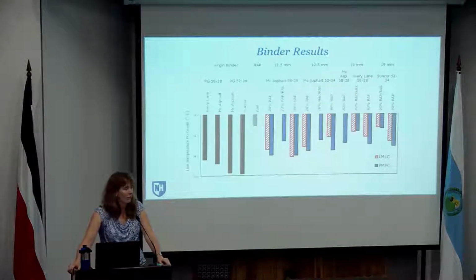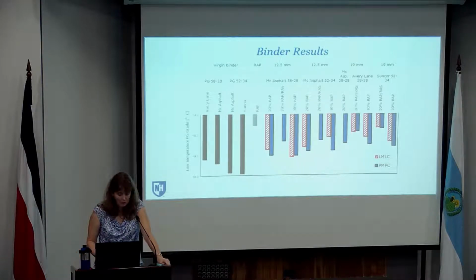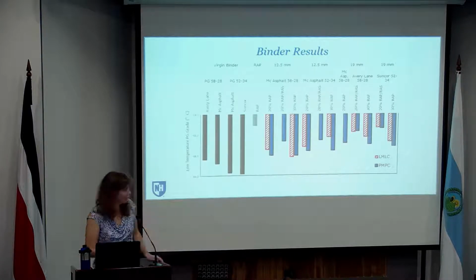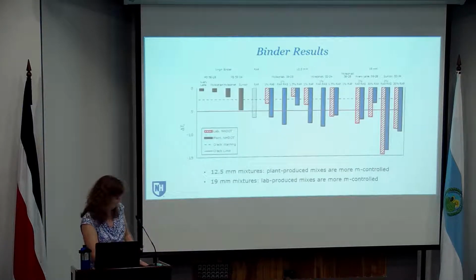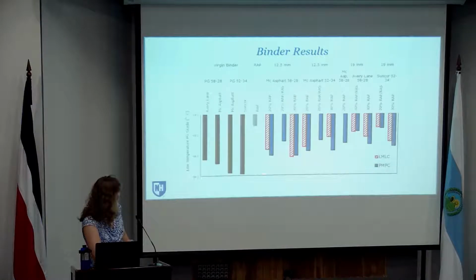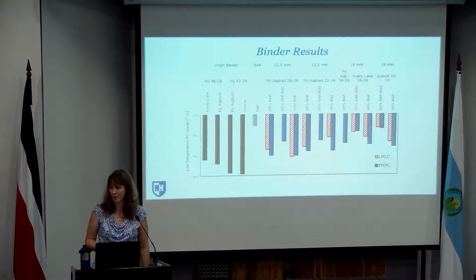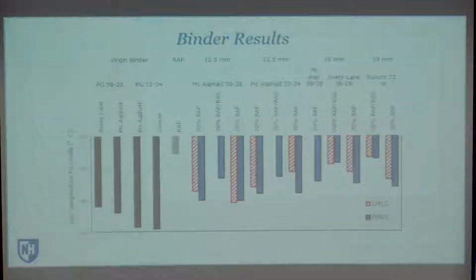Similar graph except for on the low temperature side. And so these are laid out in the same order. One thing to point out, when we did test the tank asphalts, the PG minus 34s didn't quite make the minus 34 grade when we actually tested them in the lab. They were supposed to be minus 34s, didn't turn out to be quite minus 34s, so they were borderline to start off with.